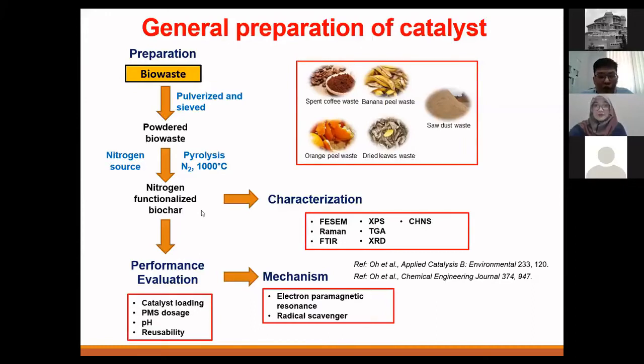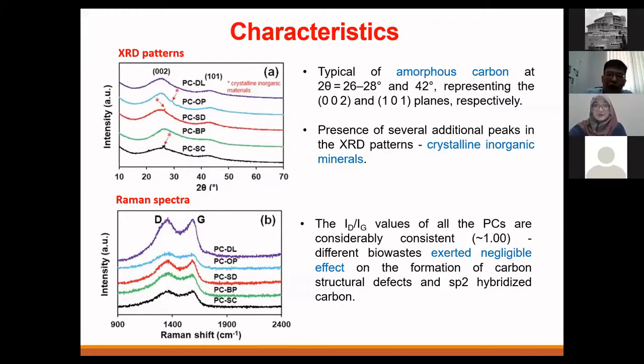This is what we call biochar. When we burn carbon, we get biochar. And this biochar has a lot of nitrogen functional groups on the surface. Okay. So what we found is that this biochar is in fact amorphous carbon, right? And of course, depending on the source that you use, sometimes you can observe some crystalline materials, and these are the minerals from the bio waste itself. Okay. So all these minerals will not affect catalytic activity because they are inert. For example, if you have sodium, potassium, all these, they are relatively inert. And they won't cause pollution.